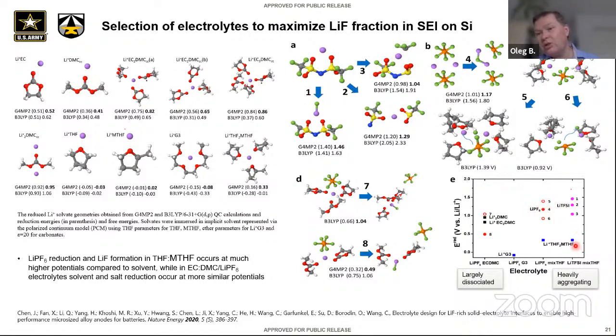TFSI could be similar to THF, except in TFSI, whenever the reduction occurs, as shown here, in order to have this high reduction potential for abstracting a fluorine from a CF3 group, you need to have lithium come into that group and form a contact, which is not very favorable, because lithium starts out being coordinated by oxygen. So it does happen, but it's a very slow reaction. And moreover, you also have lots of oxygens which eventually go to oxides and other components.